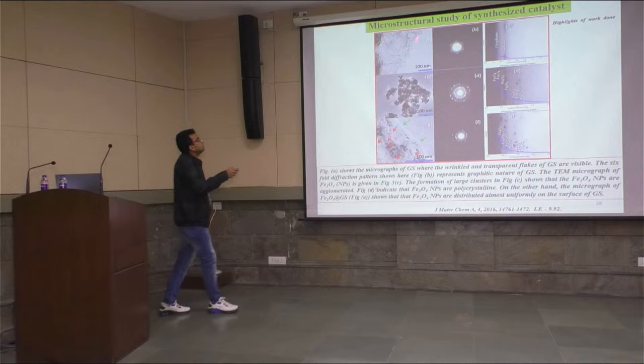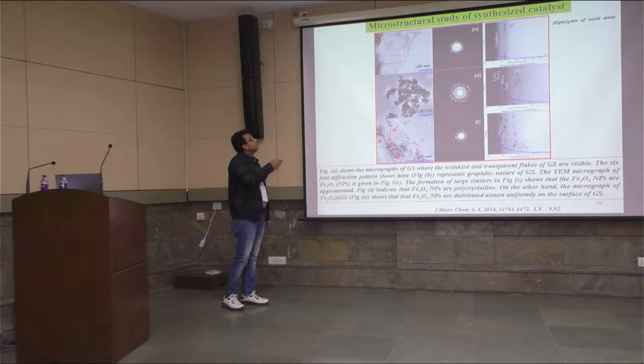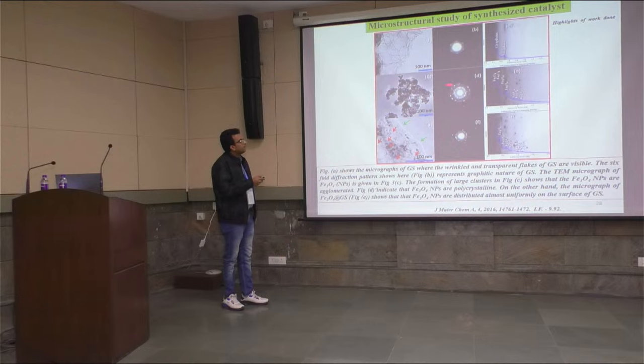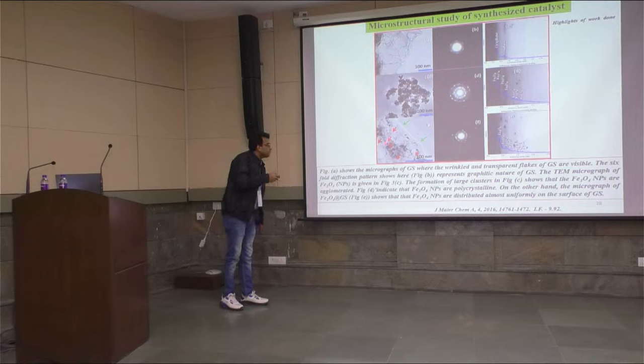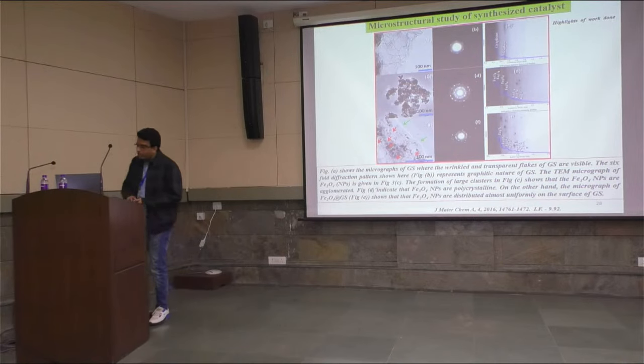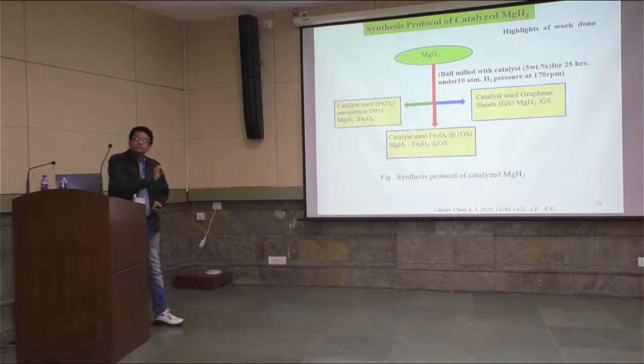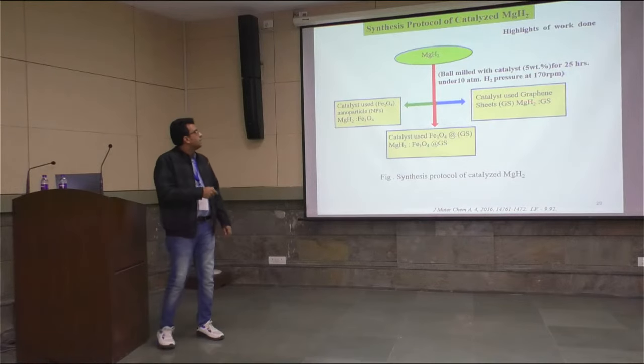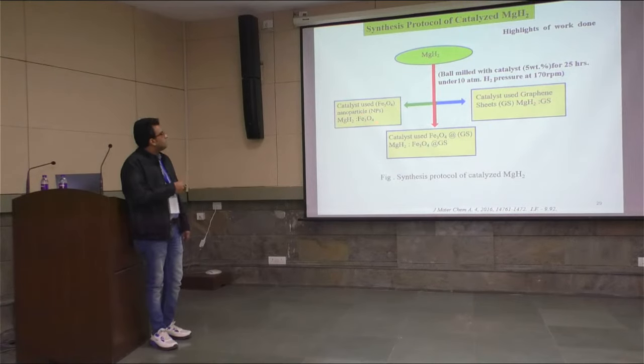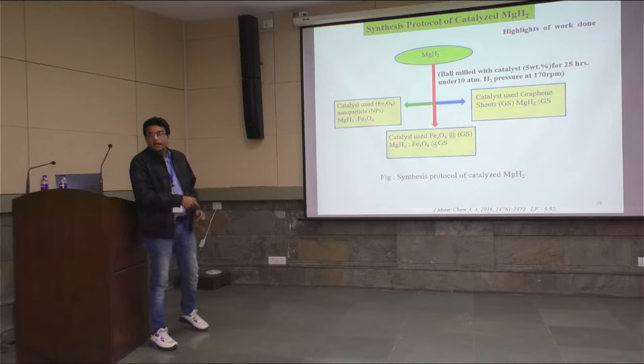So now you can see this image. This is the TEM micrograph of graphene oxide. You can see these are the graphene plates, with the 6-fold diffraction pattern of graphene. These are the TEM micrograph images of Fe3O4 nanoparticles, with SAED. Now you can see these Fe3O4 nanoparticles are highly aggregated. But if you template this Fe3O4 over graphene, you can see the particles are uniformly distributed. And we have then used these three as catalysts for magnesium hydride: magnesium hydride with Fe3O4, with Fe3O4 graphene, and with graphene.